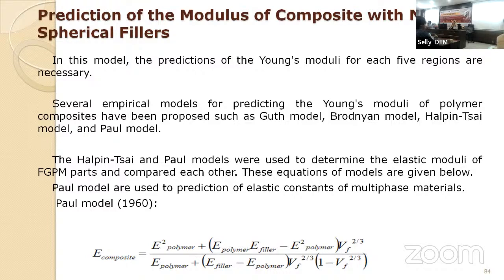You can see these equations of the models below, and the Paul model is used for predictions of the elastic constants of multi-phase materials. They use the polymer Young's modulus, they use the filler elastic modulus, and the volume ratio is important.